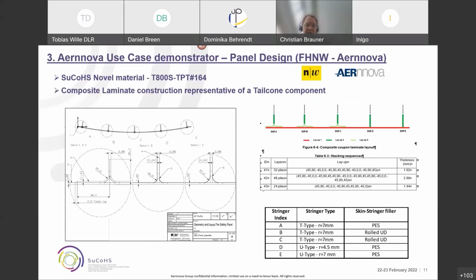This was special because for cyanate ester systems, you typically need a higher temperature than the standard autoclave temperature of 180 degrees. Then this material was also toughened, and we converted it together with the company NTPT to a thin ply prepreg with an area weight of 60 GSM. And we performed manufacturing using AFP as well, but this demonstrator was done in a hand layup.